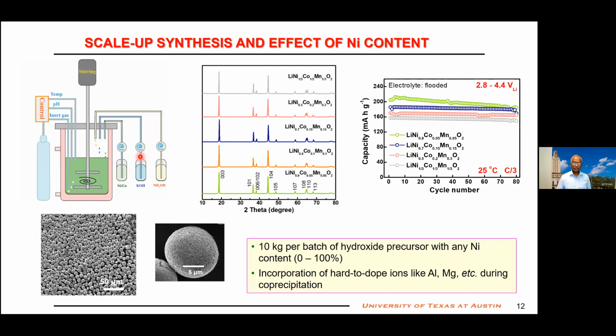Third, we also have fantastic analytical capabilities at UT Austin. So we can cycle these materials for thousands of cycles, take the cells out, electrodes out, and analyze to understand what is going on. With that, we have developed a lot of interesting stuff, so I will quickly present some of them. You see here, this material is 33% nickel. When you go to, say, 90% nickel, capacity is increasing, but cyclability is fading. So that's a challenge. You can increase the energy density, but cyclability will decrease.